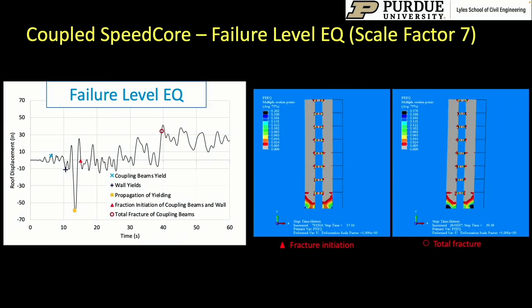But when you consider the failure level earthquake, all those events that we had identified occur in the right sequence. You get yielding of the coupling beams, followed by wall yielding, propagation of yielding along the height of the structure, initiation of fracture in the coupling beams, and then finally total fracture of the coupling beams along the height of the structure. So that was the seismic response that was programmed into the system by the capacity design principle, and it gives us exactly that.